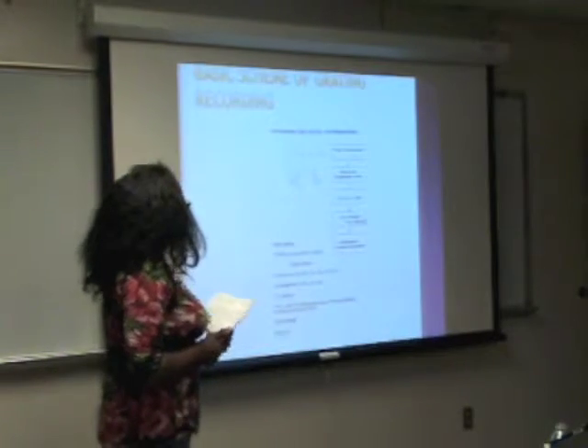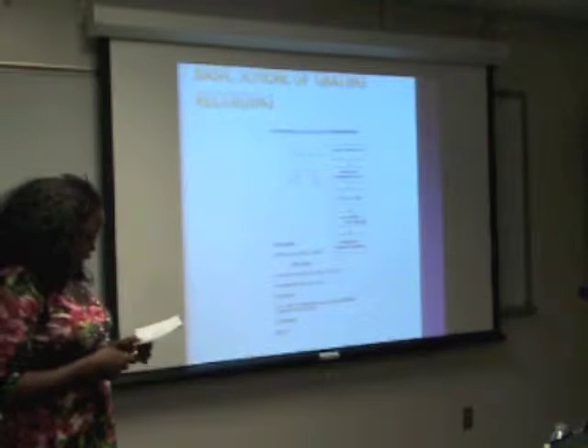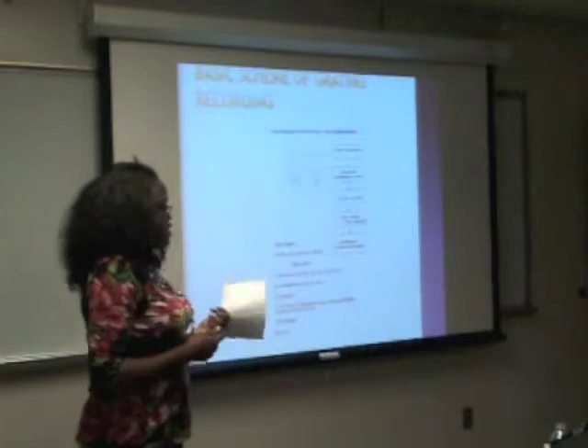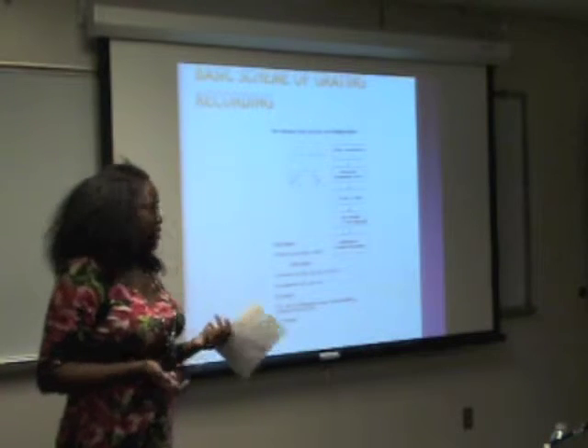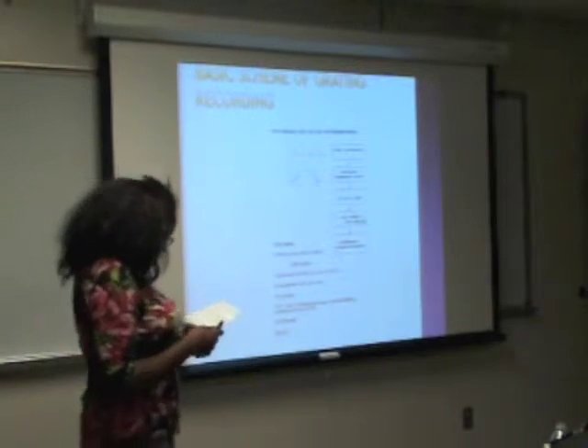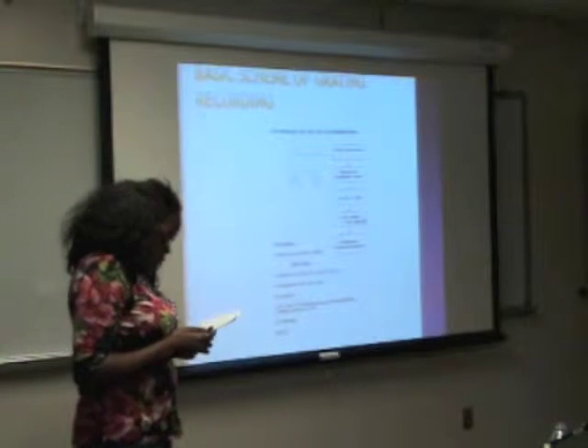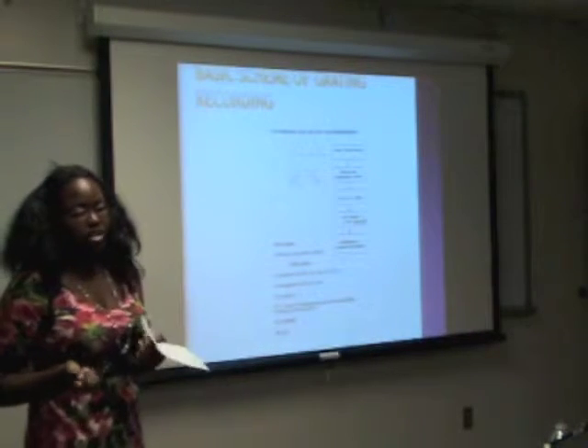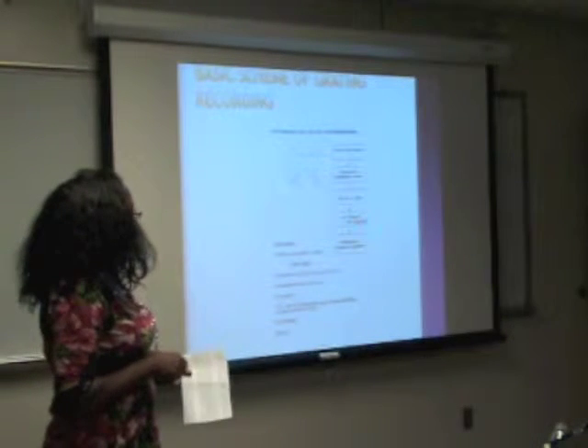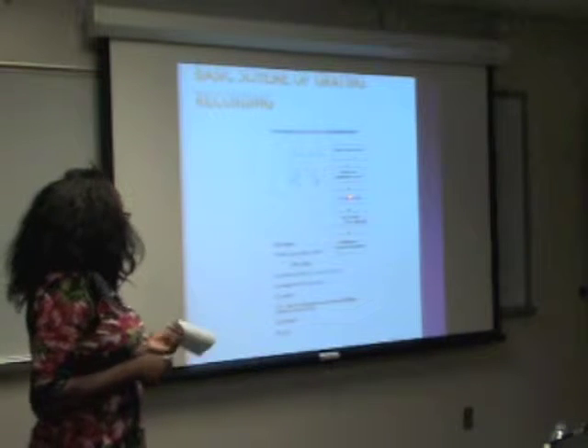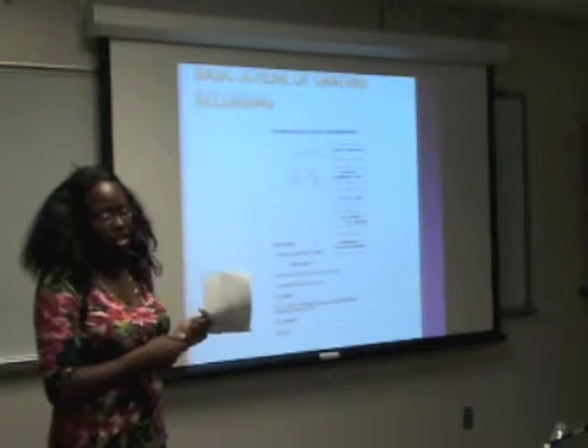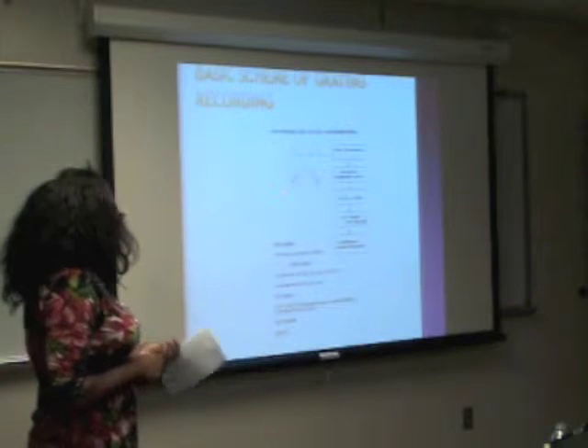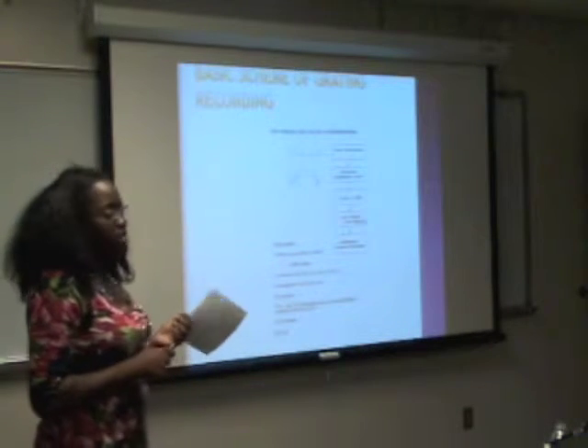This is another basic scheme of the grating recording of the photorefractive crystal. The example we used was the iron-doped lithium niobate crystal. During the grating recording in the photorefractive crystal, photo-excitation of the charges begins, and once the electrons start to move around, this is called a diffusion drift or a photogalvanic current. This process will cause a change of refractive index. Some examples of materials that can be used are regular crystals, polymers, or liquid crystals.